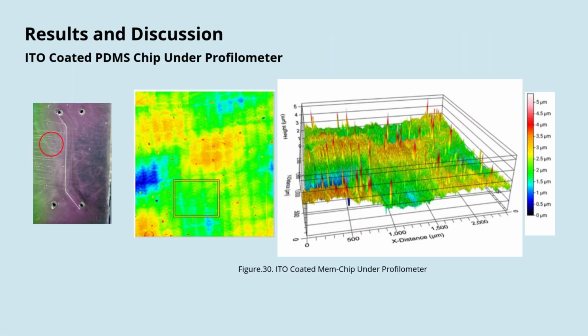Under the profilometer, it can be seen that the roughness of the PDMS surface caused some peaks and valleys in the coating. While some points are between 400 nanometers and 500 nanometers, most of them are lower than 200 nanometers. So for future work on PDMS, the layers should be thicker than 300 nanometers while the plateaus can be seen.